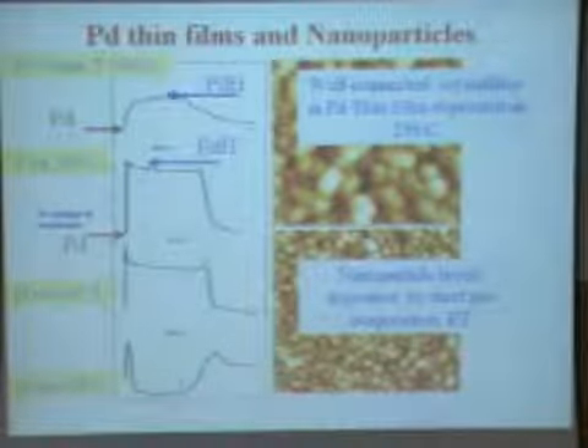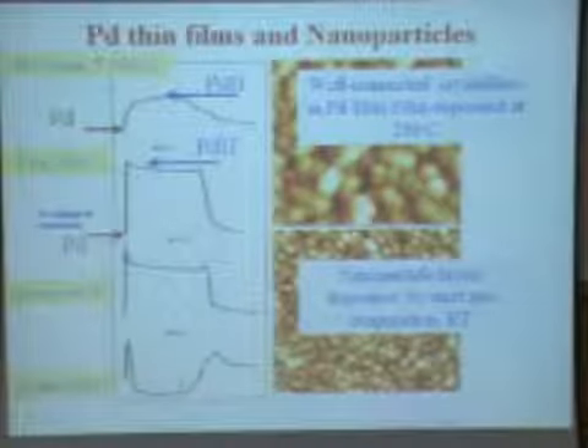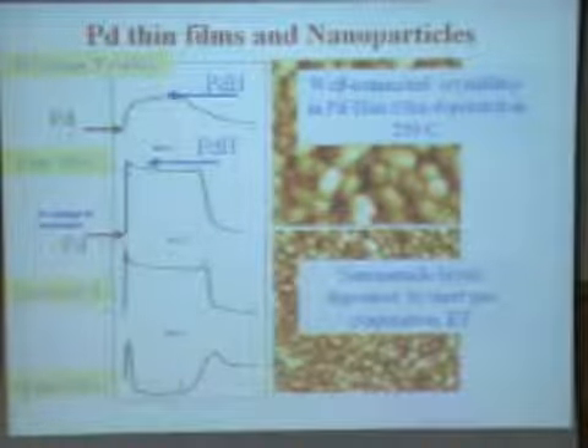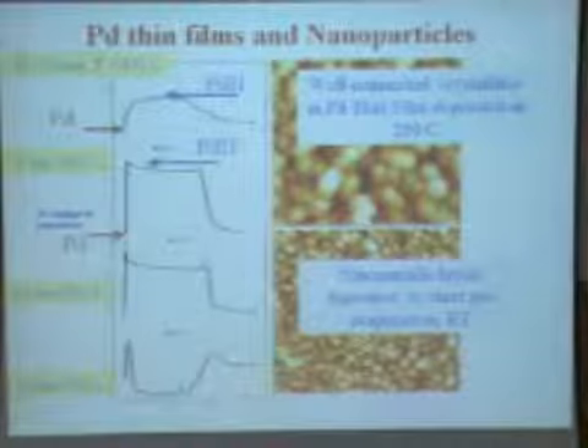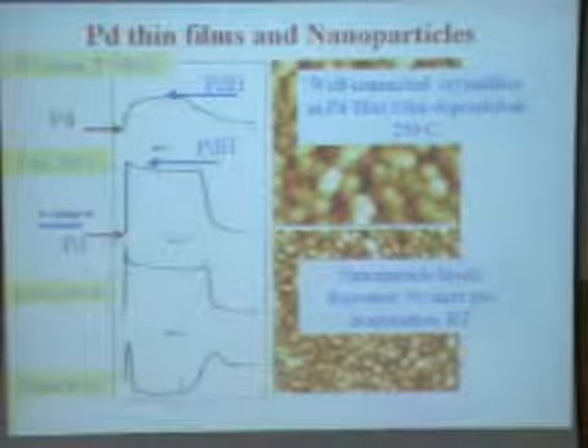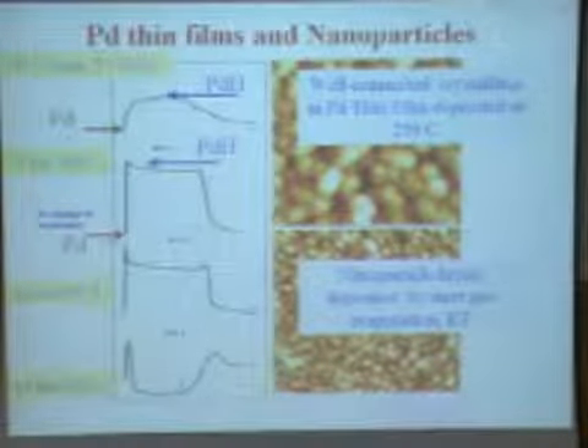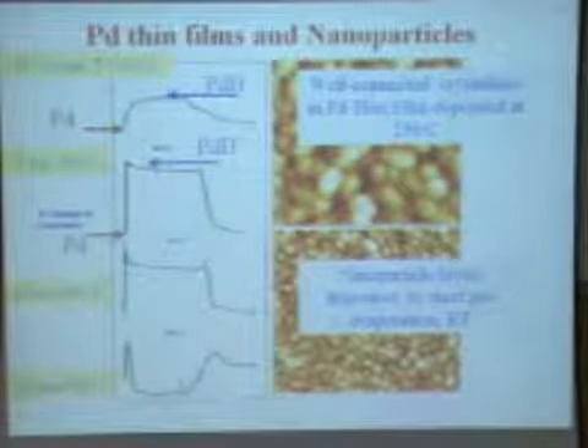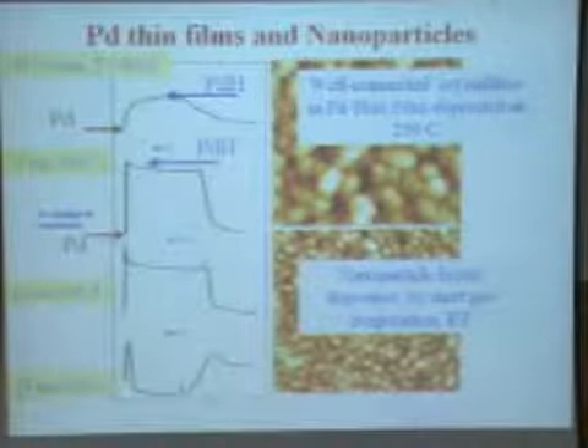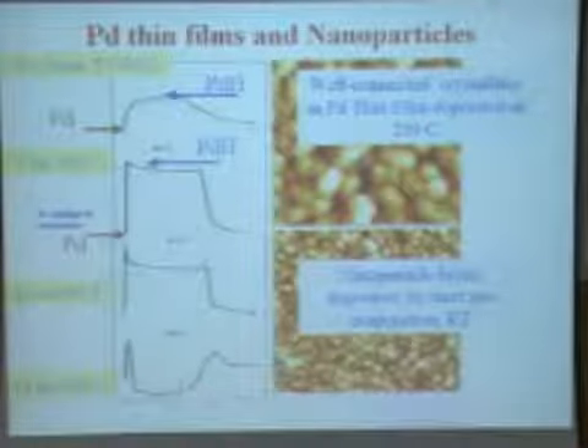What has happened is, in thin films it was like this. When we have nanoparticles, you can see that the resistance suddenly goes up, and it slowly comes down. Here, it's even faster, and the amount of decrease is also very large. Compare the first case with this case. In the first case, as the palladium is exposed to hydrogen, the resistance slowly increases and saturates. In this case, the electrical resistance goes up and comes down immediately, while the material is still exposed to hydrogen. At this point, you remove the hydrogen. The resistance again goes up and again comes down. There is a dramatic effect.